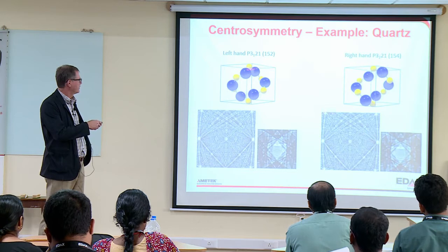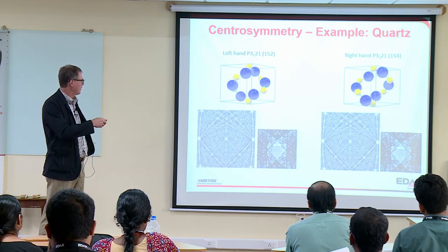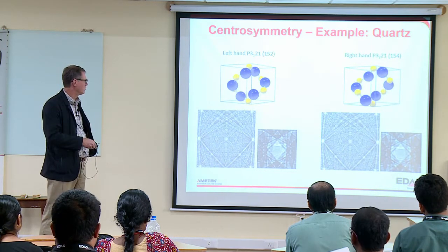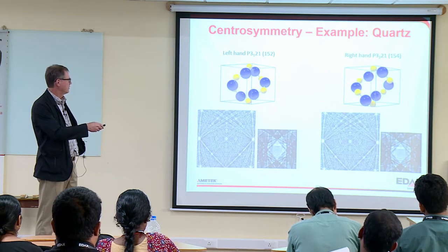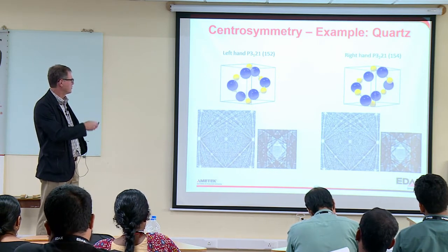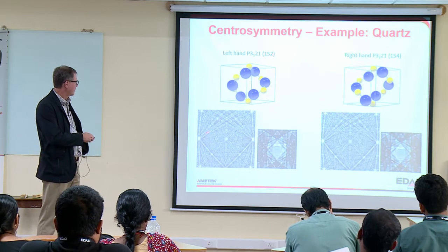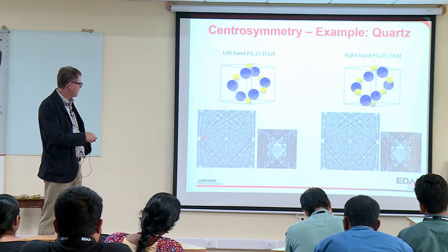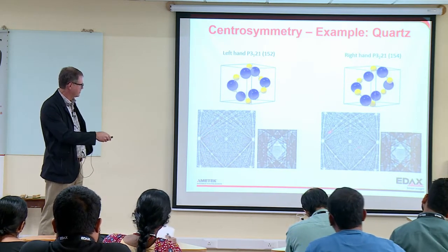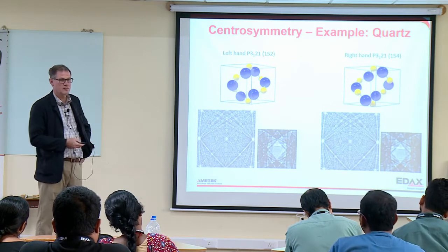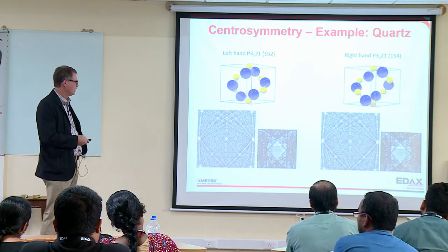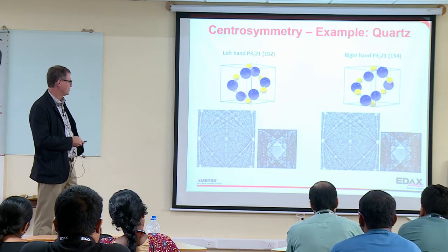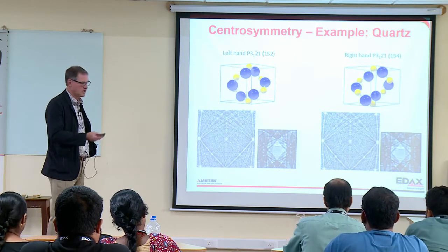So here, for example, is quartz. There's two types of quartz, left-hand and right-hand quartz, and you can see the space groups are slightly different. And what you see here then is, if you look at these patterns, the positions of the bands, the intensity of the band all look exactly the same. But if we go into really fine detail, and these are, once again, simulated patterns,